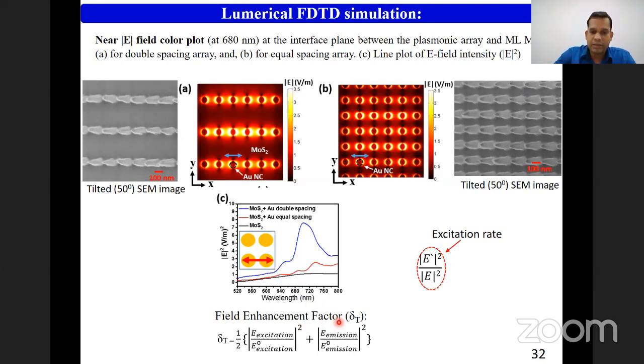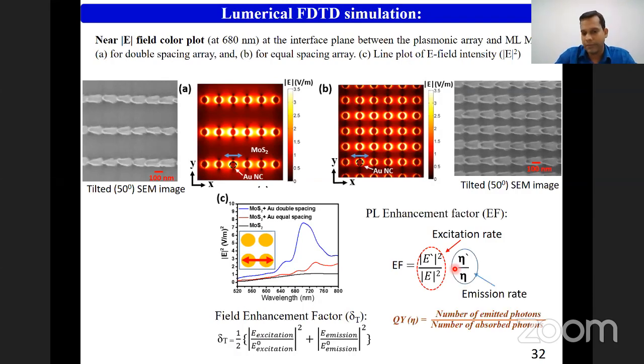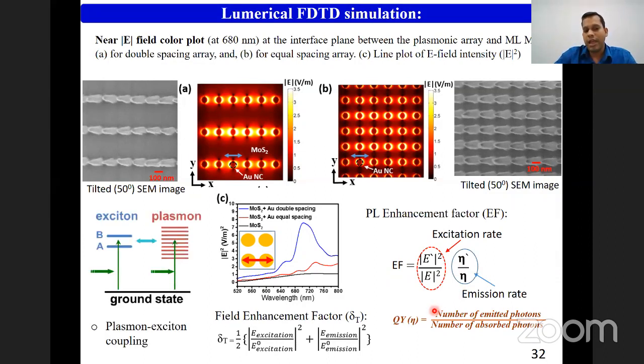And this field enhancement factor has a direct link with the PL enhancement factor, because the excitation rate depends on that field enhancement factor, and that can have a direct link with emission rate. This plasmonic array provides the local density of states to populate the A excitons, so that their recombination will give higher luminescence. So that coupling is very strong, and we can further use that for modulating this luminescence.